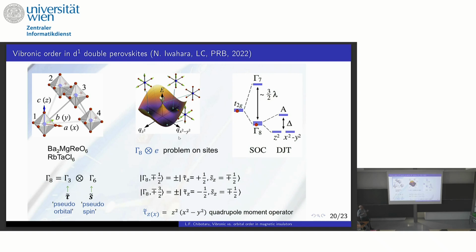Because lambda, the interaction, is not infinite, this produces some warping of the trough, and you have a kind of hindered rotation. So the ground state is a plus-minus 1/2 vibronic doublet. But the next vibronic doublet splits into A1 and A2, and these approach the ground state doublet. So you have to consider 3 states. These are Kramers doublets. These are vibronic states which rotate. These are hindered rotation.